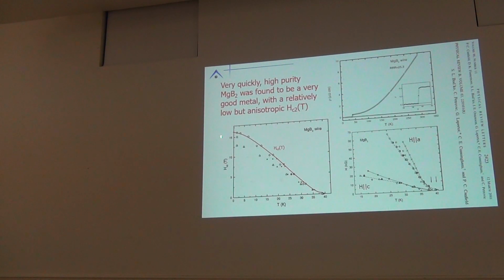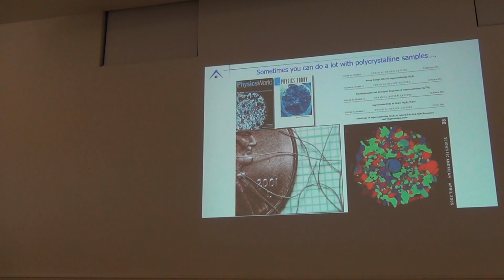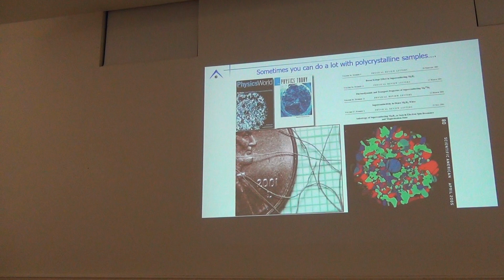Okay? Now, we can map out HC2 in these pure materials. It's actually fairly low. It's 15, 16 Tesla. Okay? The resistivities are fantastic. You have very large RRRs. You have minor anisotropies. But just to sort of impress on the students, you don't have to have a single crystal to do good research. You can do a lot of good stuff with polycrystalline samples as well.